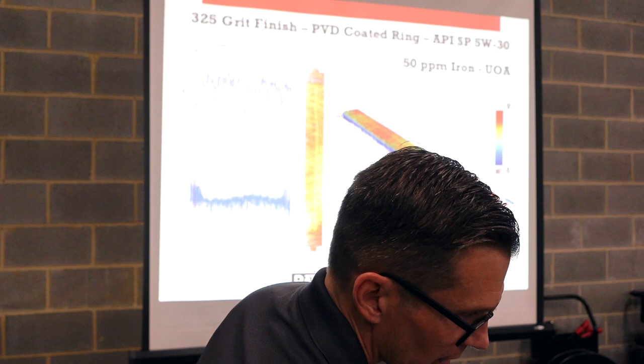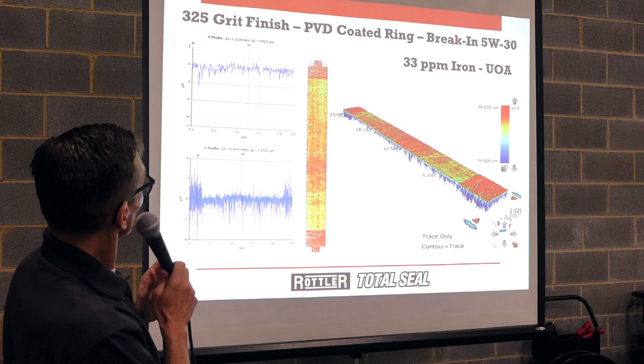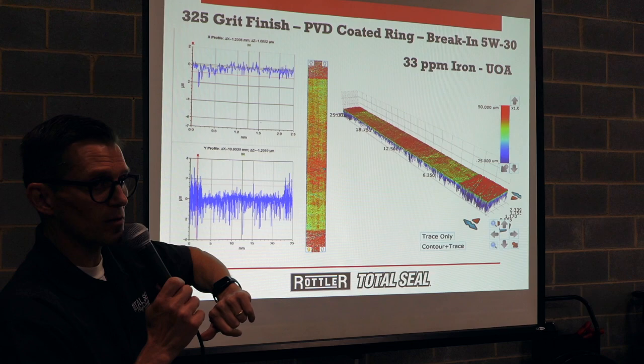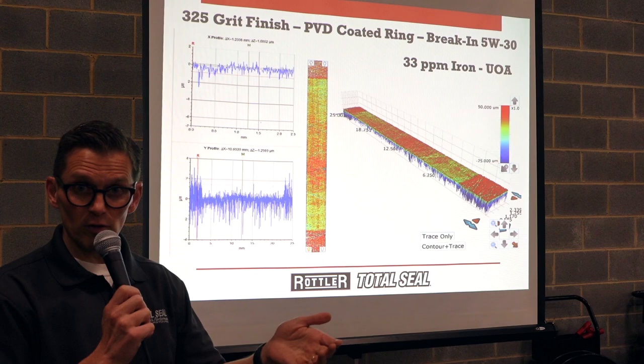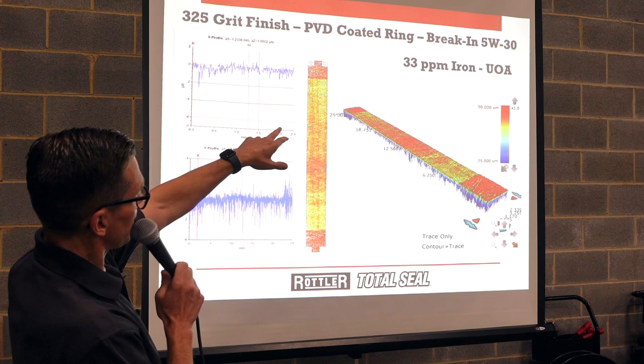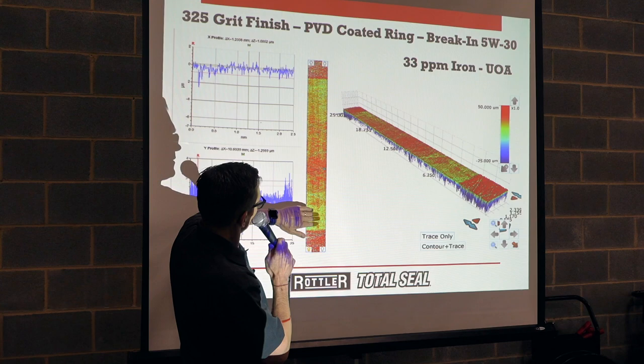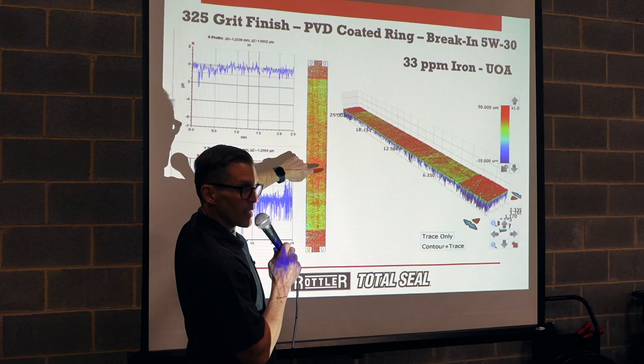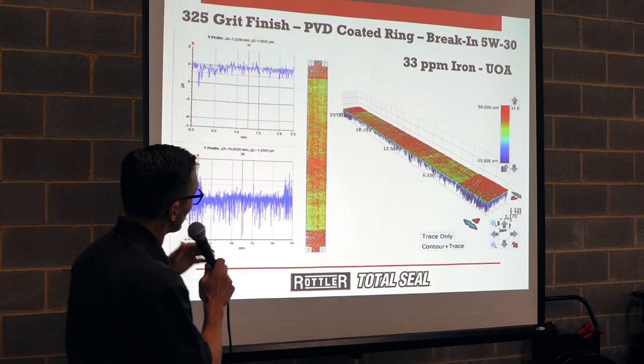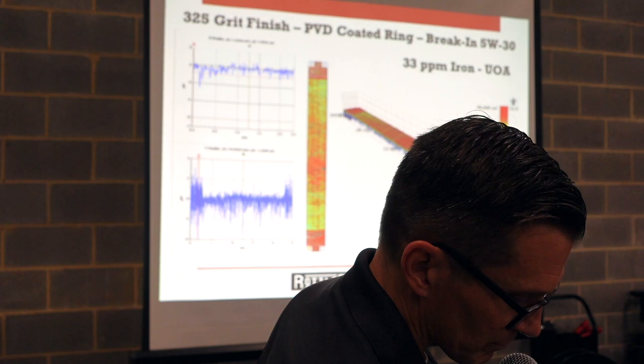Then we actually brushed it. This one we swapped the oil from the regular API oil and put in break-in oil, with the correct chemistry: higher ZDDP, fewer friction modifiers, less detergent. Now the wear drops down to 33 parts per million, and you see there's no more debris. And like before, where the ring stops, it gets lower mid-stroke, hydrodynamic, there's less wear, back and forth. So it's very even and uniform. Things are getting better as we add coatings and change the oil chemistry. Things are getting pretty cool looking.